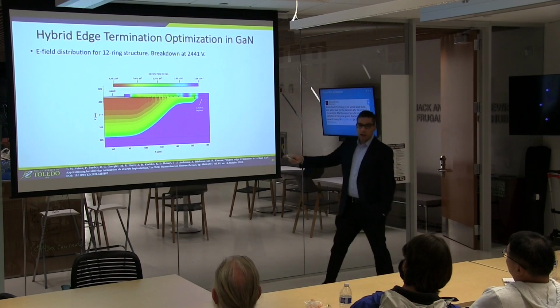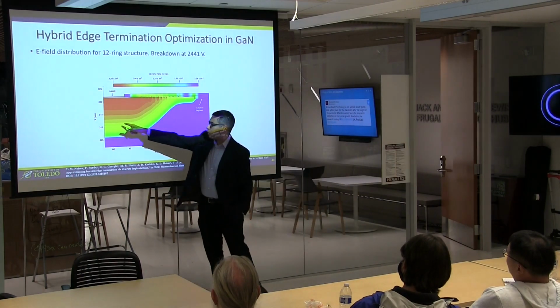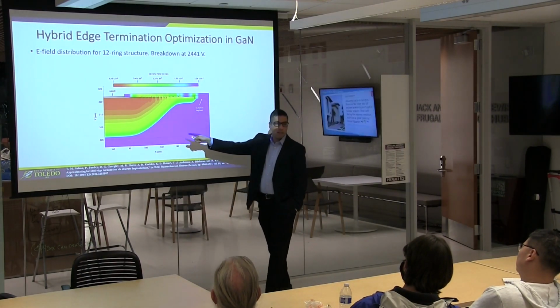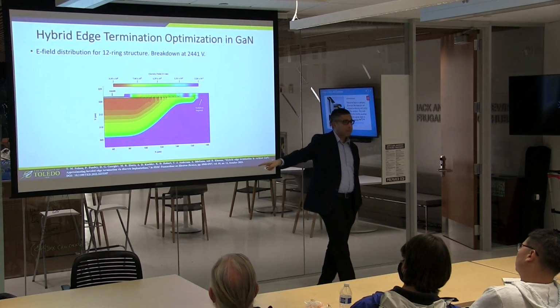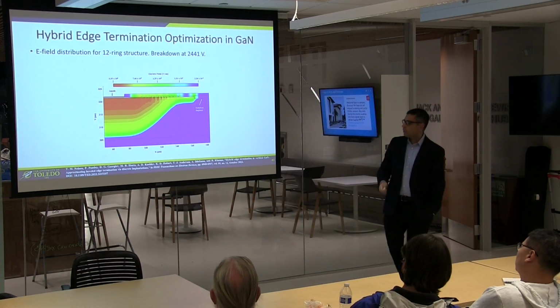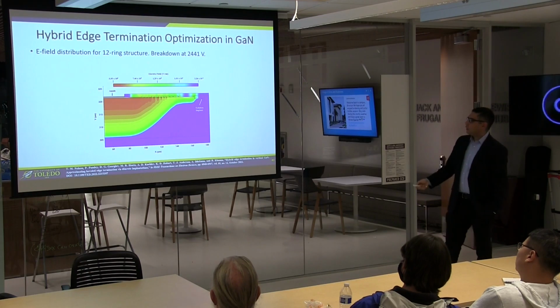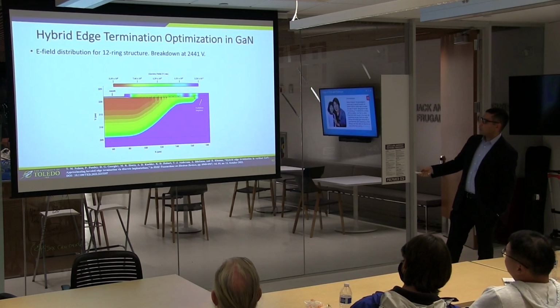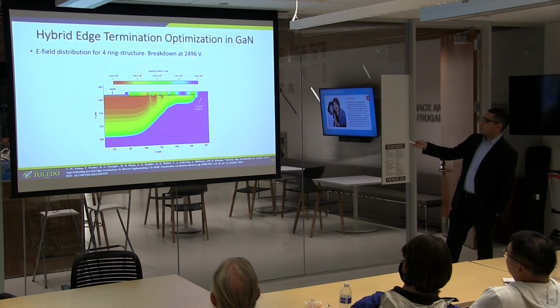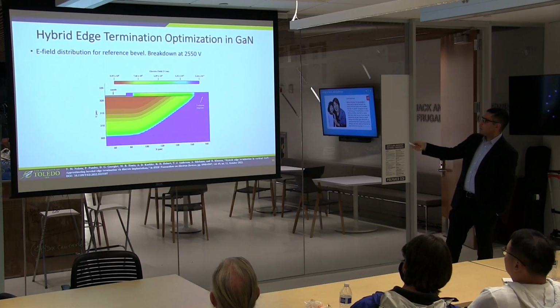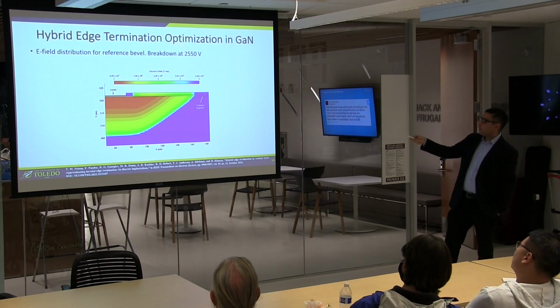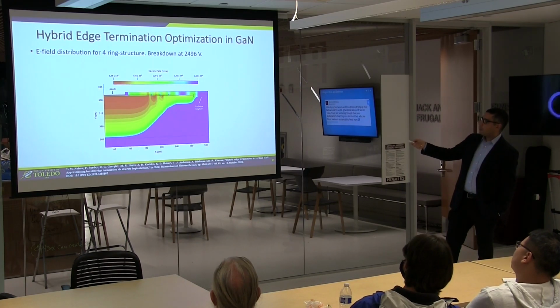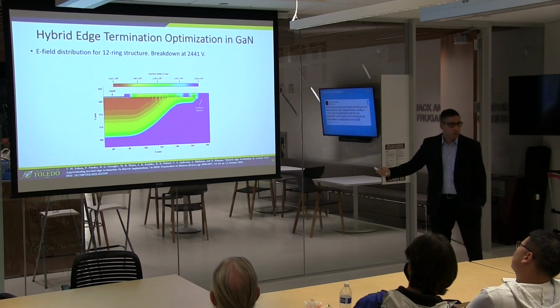What we do is we do a cut line. At any given point, we do a bunch of cut lines to study how the E field changes at any given point along the PN junction. And I'll show you that momentarily. What about this is the 4-ring structure. What about the 12-ring structure? Now, the 4-ring structure is breaking down at 2,500 volts. Let me go back a second here. The reference one's 2,550. The 4-ring optimized structure, 2,500 volts. And the 12-ring, 2,400 volts about.